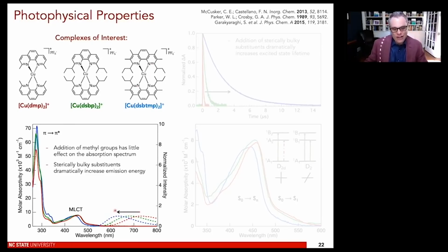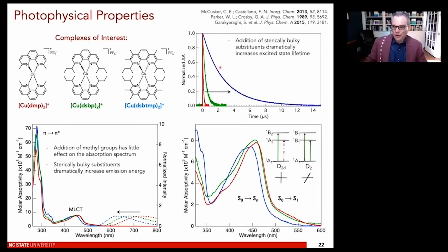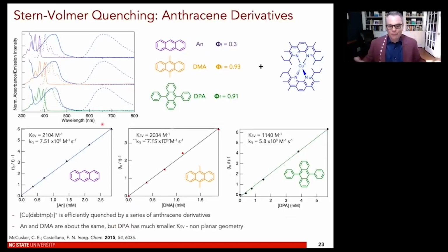So what does that do? Well, energy gap wise, this blue one is the longest lifetime, which is shown here. The middle one is the next longest lifetime, and then DMP has a very short lifetime. So this is good for the lifetime component that we need. It's energetically the least Stokes shifted because it doesn't distort. Therefore it has the highest excited state energy, which is then valuable for driving photochemical upconversion to a variety of substrates. There's a lot of other stuff here, which I won't get into, but the idea is that you can systematically control these molecules, and they actually wind up being better than the ruthenium(II) compounds in photochemical upconversion.